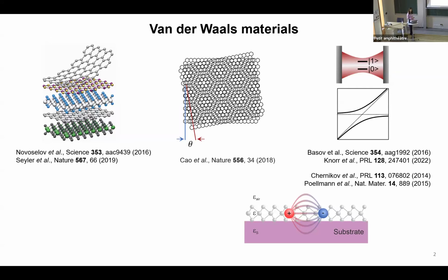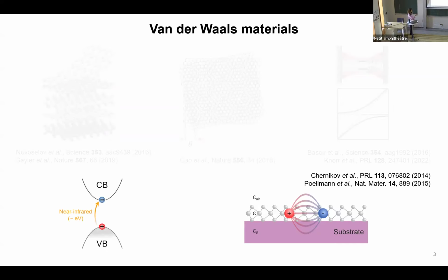Just to remind you what excitons are: when you shine a near-infrared, electron volt pulse on a semiconductor, you excite electrons from the top of the valence band to the bottom of the conduction band, and this way you form an electron-hole pair. Due to reduced dimensionality and reduced dielectric screening, you form a bound quasi-particle of electron and hole, which behaves very much like a hydrogen atom. Its constituents are one positive charge and one negative charge, so it is an artificial hydrogen atom. The electronic transitions of these excitons are described by excitonic orbitals, like 1s, 2p, 2s, etc.